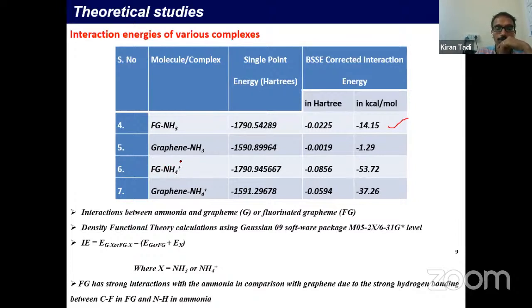So this ammonium ion in the blood, ammonia, if you would like to detect, then also it has the highest interaction energy in comparison to the simple graphene, that is without doping, without the dopant of my fluorine molecule. So there is a large difference between after doping and before doping with these interactions.